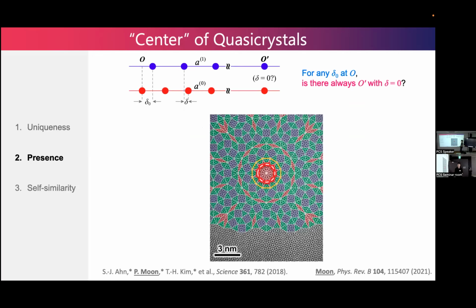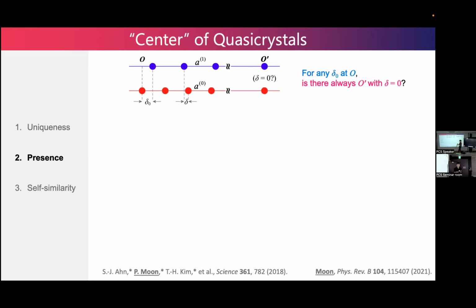Presence. So the question is, if we stack two graphene layers at 30 degrees, will there always be an exact center with delta equals exactly 0? In a one-dimensional analogy, if we stack two layers in an arbitrary configuration, will there always be a delta equals 0 point? At that time we discussed this very briefly, but we didn't care much because of the self-similarity, so we could avoid it. We naively thought that there will be, because this is an infinite structure, so somewhere there will be delta equals 0. But it turns out that it is not.